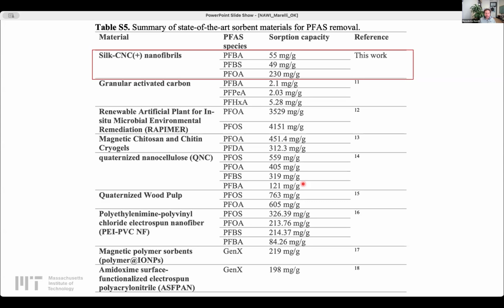Another challenge that you have with the biopolymers is the batch-to-batch variation. Typically with silk and nanocellulose, we have very good performance, extremely good repeatability. If I have one student that takes over the project from another student, with different sources of silk from different parts of the world, we have very consistent performance. For other biopolymers, the source of the polymer historically has always been a challenge. And so the extraction of the biomass has a big role in that, and we are developing protocols that are able to minimize the batch-to-batch variation. The other challenge that we have is that the self-assembling process that you saw at the moment takes time.